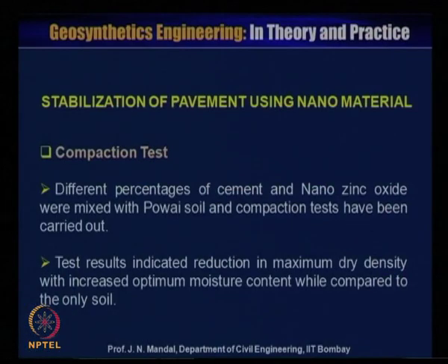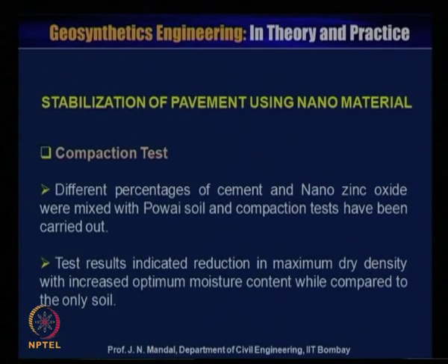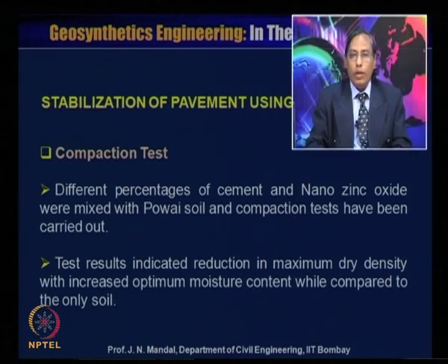Now, stabilization of pavement using nano material. We have done a number of compaction tests, and different percentages of cement and nano zinc oxide were mixed with the Powai soil, and compaction tests have been carried out. Test results indicated a reduction in maximum dry density with an increase of the optimum water content compared to the soil only.